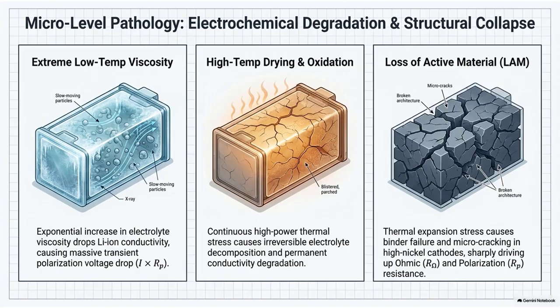Right. And these parasitic side reactions generate gaseous byproducts and solid precipitates that literally clog the porous structure of the electrodes. Like plaque in an artery. Exactly like that. Ultimately, you reach a point of electrolyte dryout. The liquid medium is permanently depleted. So wait, cold makes it sluggish, but heat permanently cooks it dry. Yes. The ionic conductivity suffers a permanent drop, raising the ohmic resistance permanently. You can't just cool the battery down to fix this. The chemical pathways are fundamentally scarred.